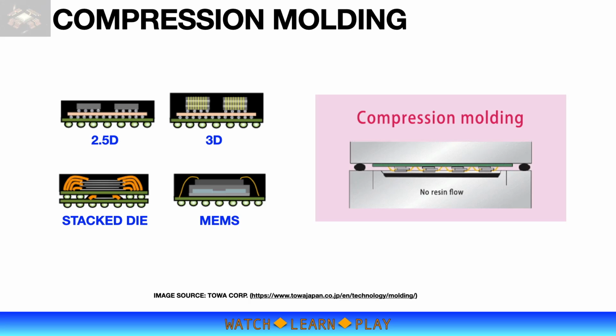Because the resin is put directly into the cavities, the compression molding process has minimum material flow. This is very important in avoiding wire sweep or damage on wire bonded devices that are using thinner wire diameter and long wire span. Also, the elimination of transfer pots and runners reduces the mold cycle time and significantly reduces mold material waste. With no mold gates and using release film, compression molding keeps the mold cleaning process to a minimum.